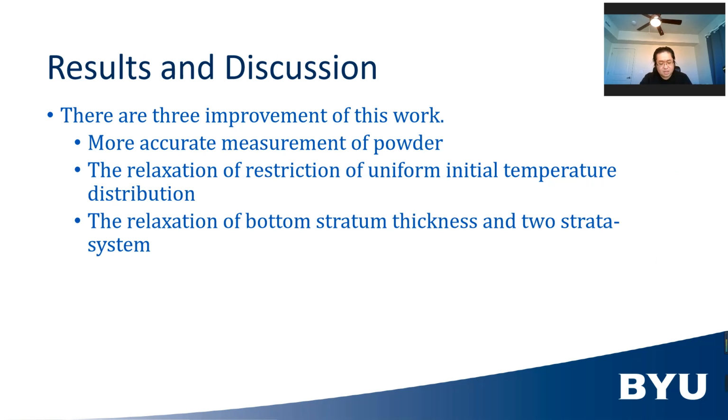Now, let's talk about the improvement of this work. First and most importantly, more accurate measurement is obtained for powder, and we can easily apply this method to other porous media, such as printed powder and BJ printing parts. In this case, an accurate correlation between thermal properties and packing density and saturation level can be obtained for BJ printed parts, if we test on different samples, of course. Now, this is the foundation to monitor BJ printing parts and the BJ printing process.